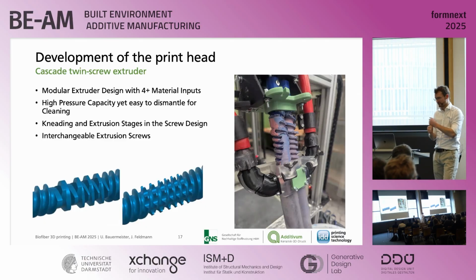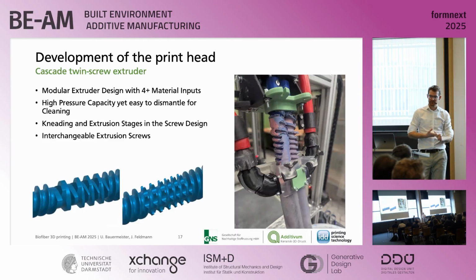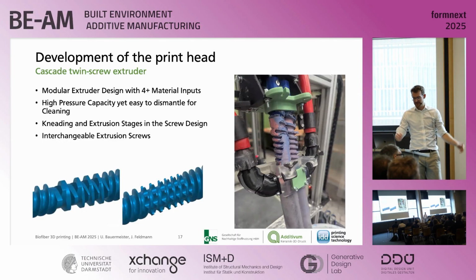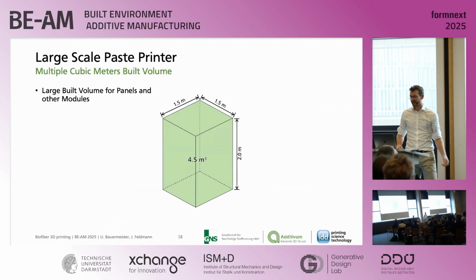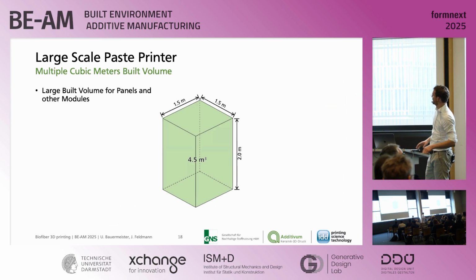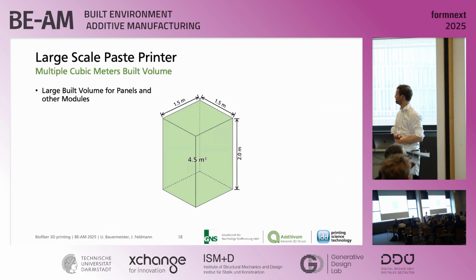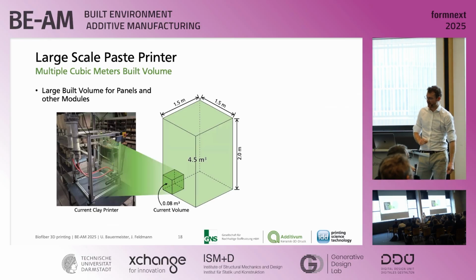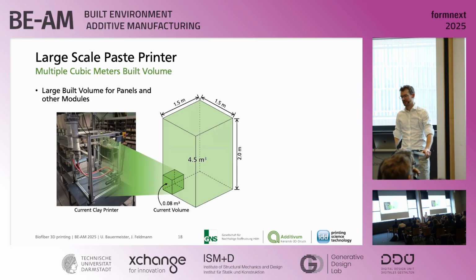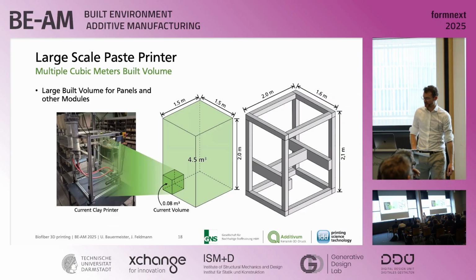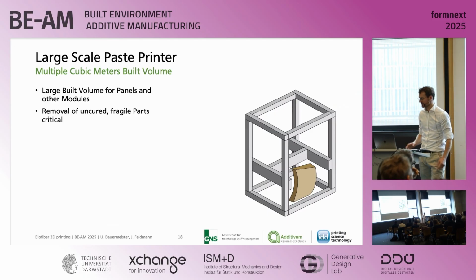All right. Now we have a material that prints fairly well. We have a print head that can print this material. What else is needed to produce big insulation panels for housing, for example? We need a big printer. We settled for now on a build volume of 1.5 by 1.5 by 2 meters, so 4.5 cubic meters, which is, by the way, I find our printers already fairly big. I mean, they have to produce urns, but 50 times more than what we are used to. And that means the printer that has to be built is even bigger than that. And another challenge we found very early is that the material, once it's placed, of course, starts already to cross-link and become a bit firmer, but we cannot remove it that easily out of the machine.